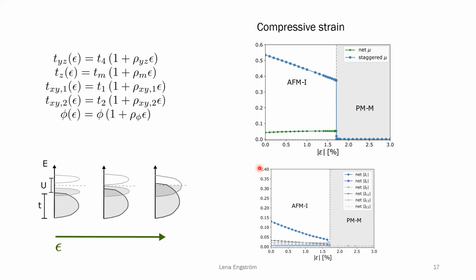To show some quick results, just for the compressive strain, we do get a decreased antiferromagnetic order, linearly, which we could expect because we linearly change the energy scale. But we see that the net moment, since we have this canted antiferromagnetic order, remains pretty much the same and actually increases a bit, since the moment seems to be coupled to having larger rotations. And eventually at some strain, we see a phase transition, so we no longer have an antiferromagnetic order.